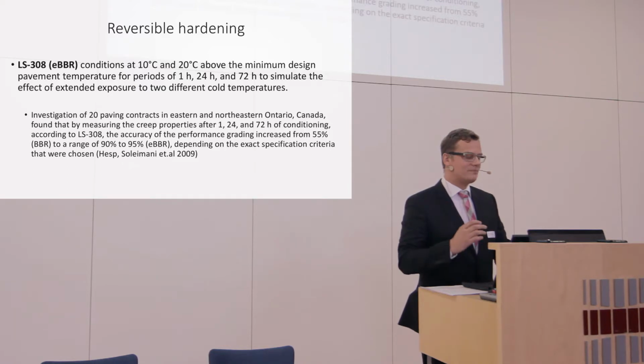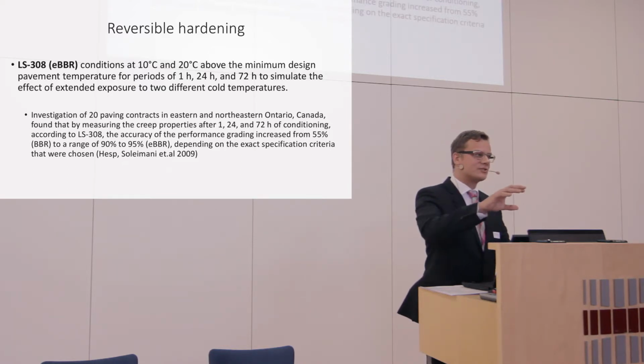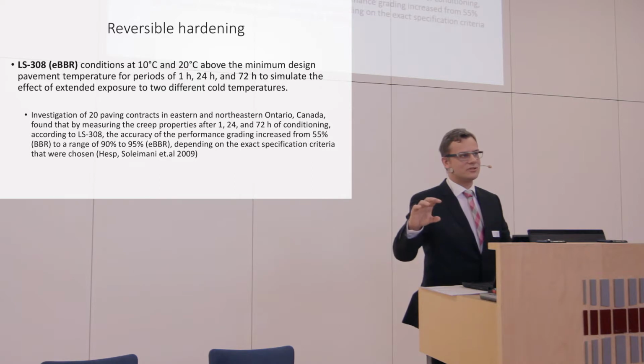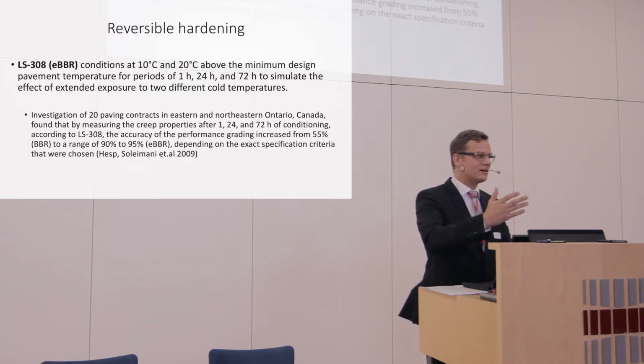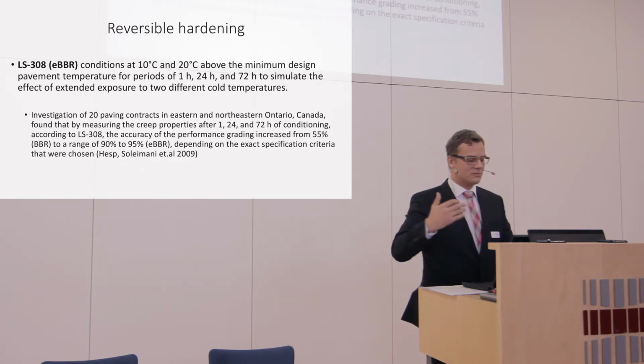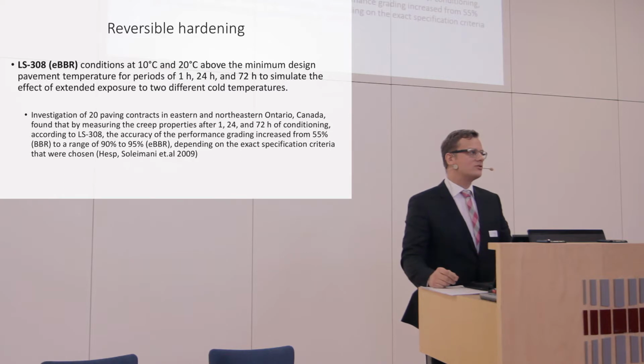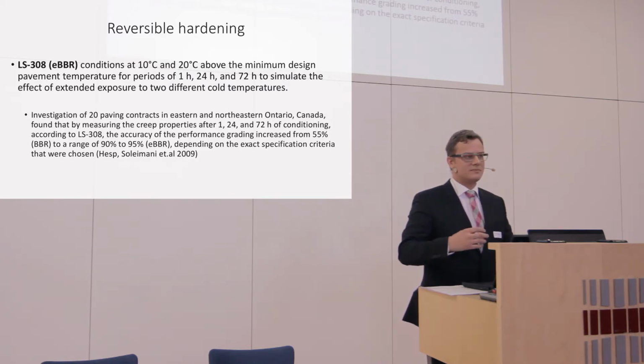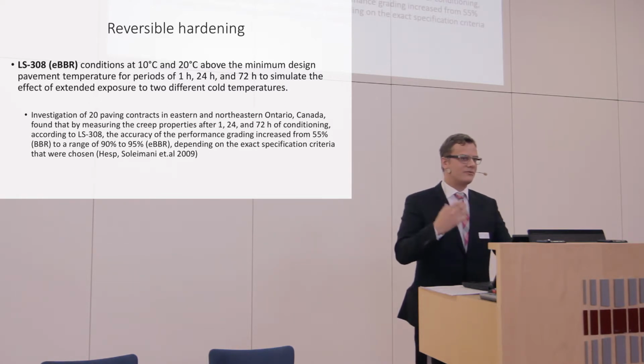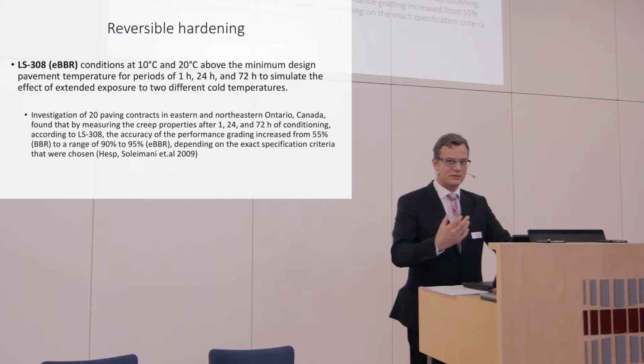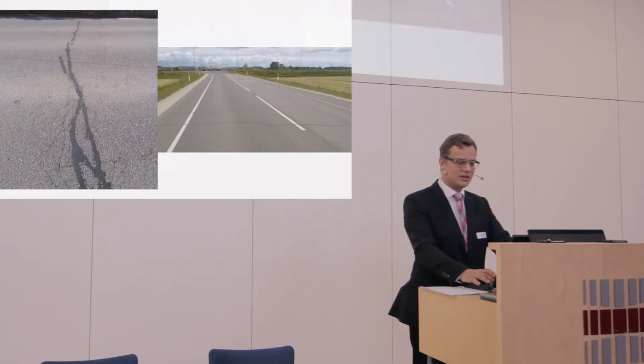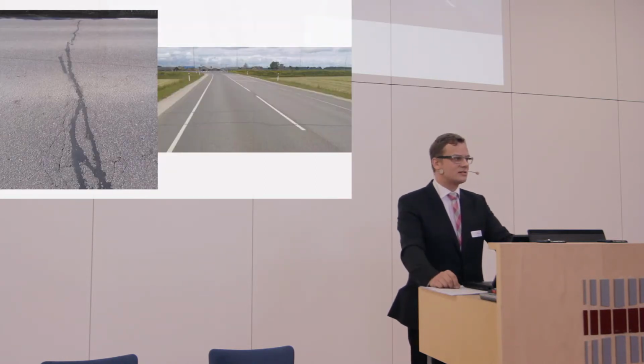So we have from 55% to 95% accuracy, whether you use a regular PBR where you don't consider reversible hardening, or whether you use extended PBR where you consider reversible hardening. So you can be much more confident that this binder will perform in a very good way on the road, and you won't see those kinds of cracks on the road.